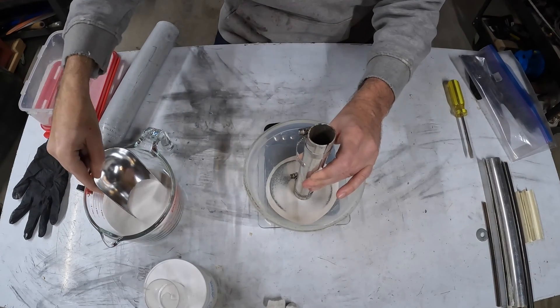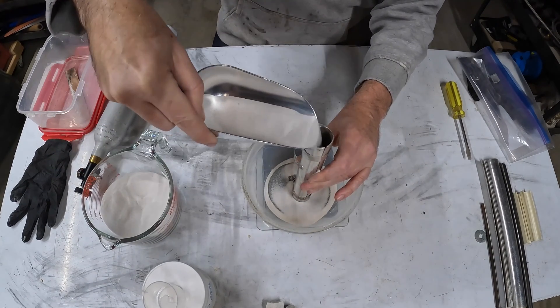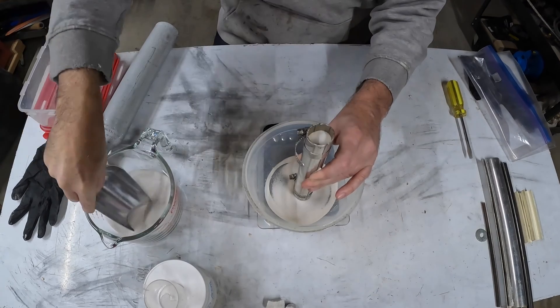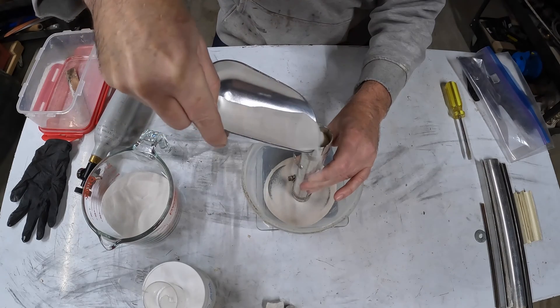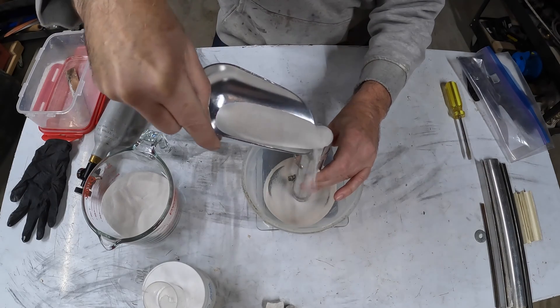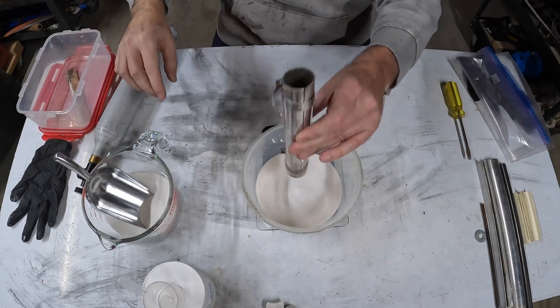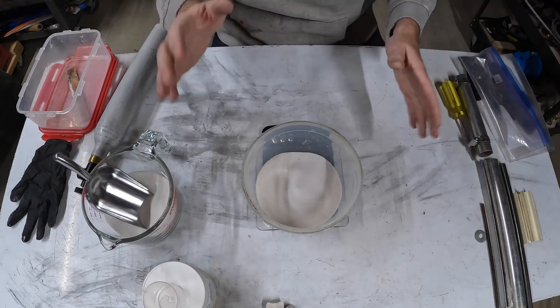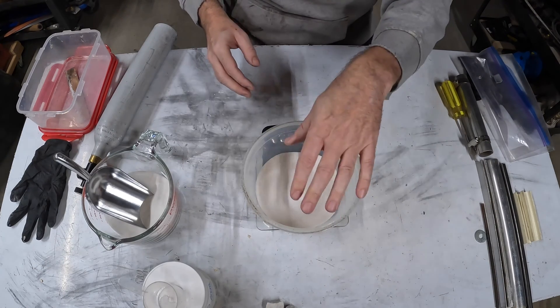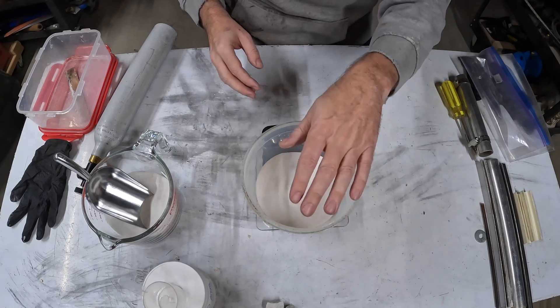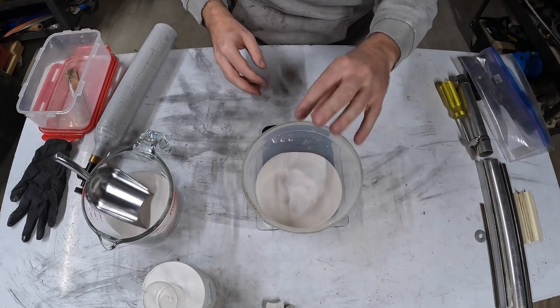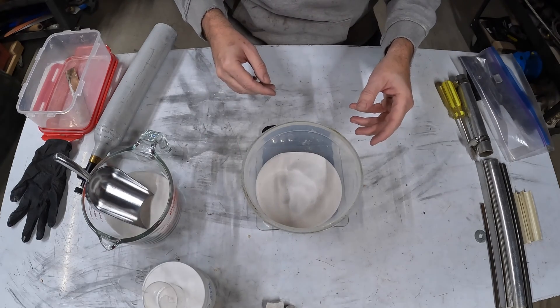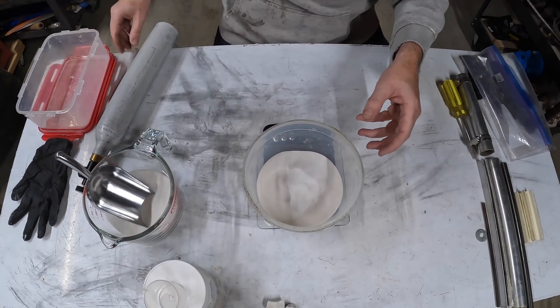Approximately, a little more is fine. The stuff you can't really make in advance because it does harden just by virtue of exposure to the carbon dioxide in the air, so you kind of have to make it as you go. Waste not, want not, so I'm going to try to be as accurate as I can. So I need about 227 grams, and the general formula is by weight, whatever weight of sand you have—and this is just silica sand—five percent by weight of sodium silicate.